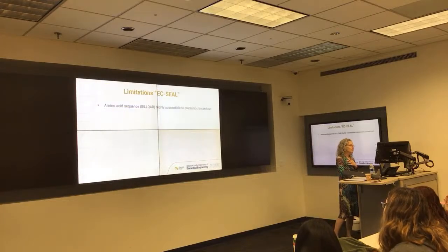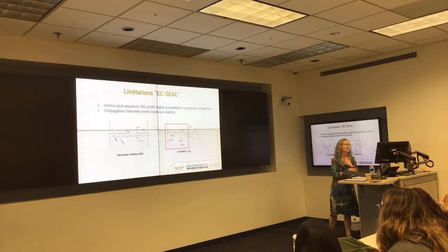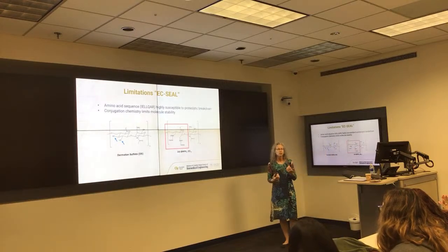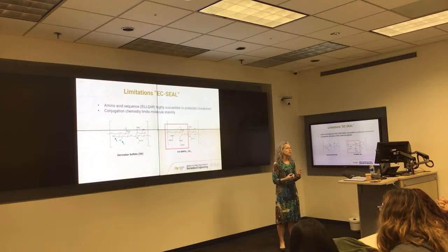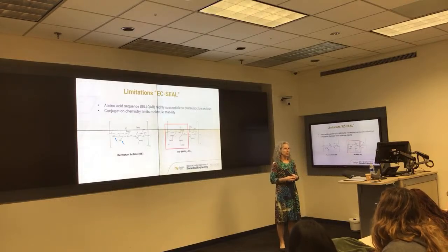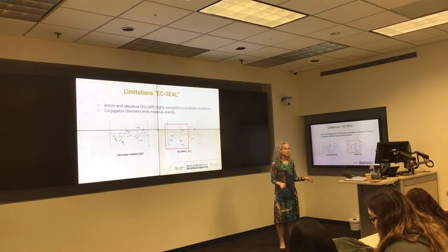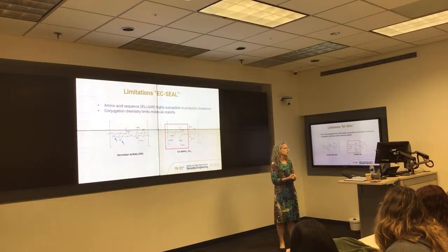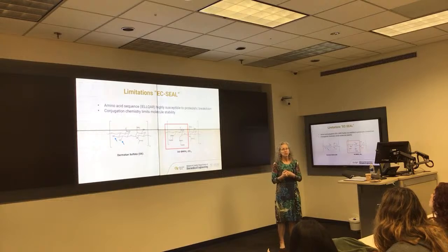Okay, so there are a couple reasons why our molecule might have a shorter half-life than we would like. The amino acid sequence we took originally was from phage display, and it's all L-amino acids, which are the normal amino acids, and we all know that proteins are subject to proteolytic degradation. And so we thought maybe the peptide's being chewed up by the proteases that are available in the inflamed environment.